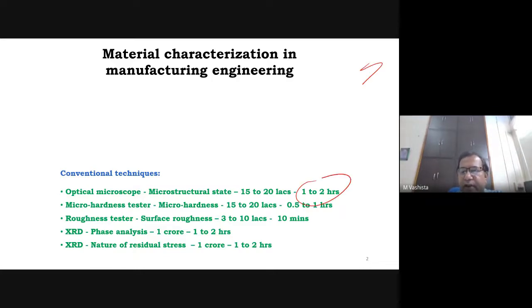Why is 1 to 2 hours needed? Because we have to consider the polishing part also. We have to polish the sample using various emery papers. After completion of the polishing process, we have to diamond polish, and then after diamond polish we have to etch the sample using a suitable etchant. So the total time of metallography analysis is around 1 to 2 hours. And in case of micro hardness testing, also we have to polish the sample.